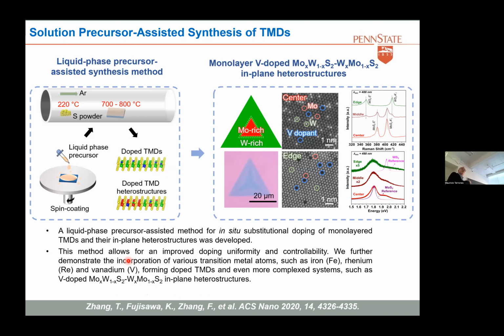In the area of TMDs, besides the mechanical exfoliation, the way to do it is basically you vaporize sulfur, you have an oxide of moly or tungsten, and you just heat it, and then you get the monolayers next to a substrate that they grow. And it was very easy to make. So I think that opened up lots of things. What we are doing here is a little bit different, but the point is we want to introduce specific atoms in the TMD lattice, and you will see that we have some control of where we can place these atoms as well.